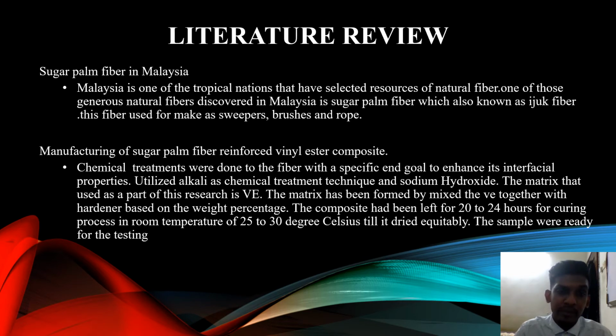Chemical treatments were done to the fiber with a specific end goal to enhance its interfacial properties. Alkali was utilized as the chemical treatment method, using sodium hydroxide. The matrix used as a part of this research is vinyl ester, which is known as VE. The matrix was formed by mixing the VE together with the hardener based on the weight percentage.